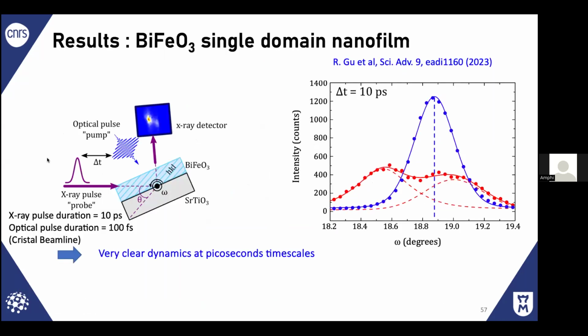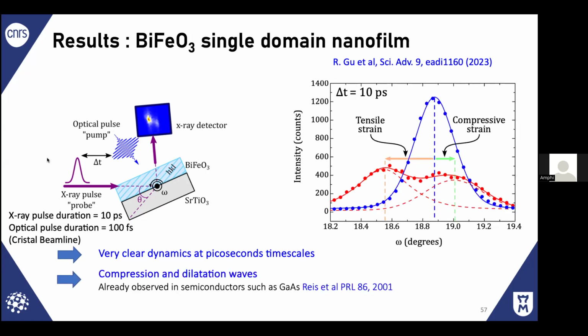And this is typically the experiment we can see. This is the Bragg peak, and in red is how the Bragg peak changes as a function of time. So the question is, when we first saw that Bragg peak evolving, let's say two Bragg peaks, there is a phase transition? No, it's not a phase transition. If you remember, that part is just due to the fact that, as I told you, when you shine light on a solid, there is a specific spatial distribution of the strain.